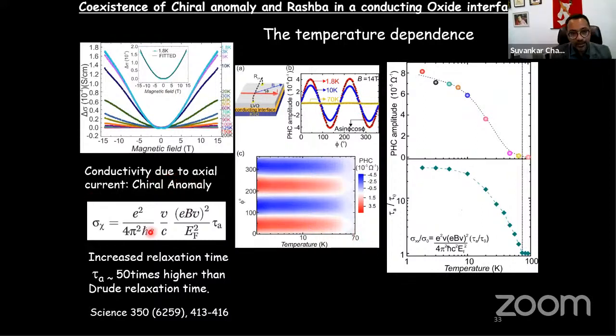And why should you see negative magnetoresistance? Negative magnetoresistance means that when you apply a magnetic field, your resistance decreases, that is, your relaxation time increases. So in the case of Weyl physics, people say that this corresponds to what is known as axial relaxation time, which is different from the normal Drude relaxation time. And when you apply I parallel B, this tau A becomes larger than tau 0. That is, your axial relaxation time should be longer than your Drude relaxation time. We have fitted this with our system, and we could see a 50 times enhancement of this axial relaxation time. And this is the temperature dependence of tau A by tau 0, and this vanishes at around 70 Kelvin.